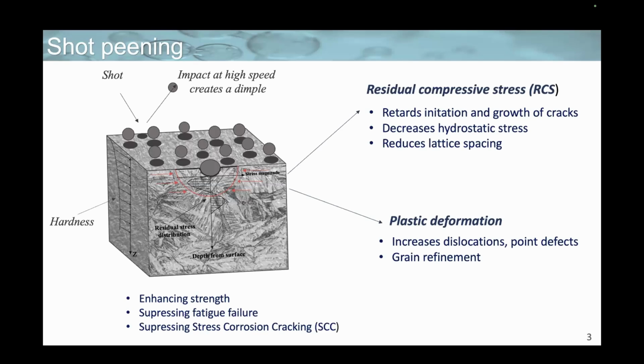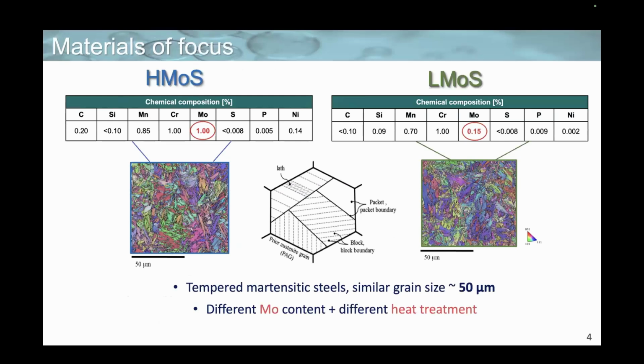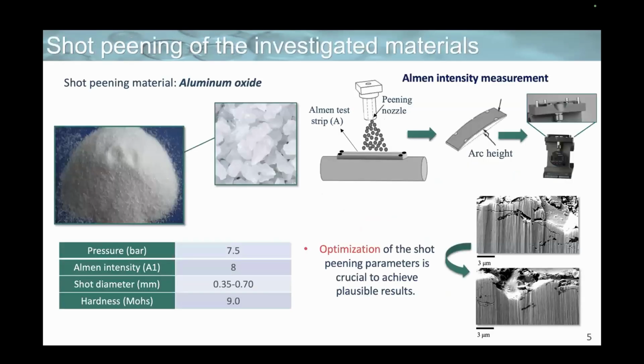Generally speaking, shot peening is a well-known and utilized method in industrial applications to enhance the strength of different components or to suppress fatigue failure and stress corrosion cracking. However, in terms of hydrogen embrittlement, the knowledge about shot peening is very limited, especially in the area of high-strength martensitic steels, and results appear to be controversial. Two materials of focus in this research are denoted here as the high molybdenum steel and low molybdenum steel. They have a similar microstructure and they differ in the content of molybdenum and in heat treatment.